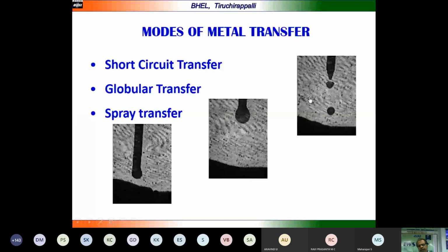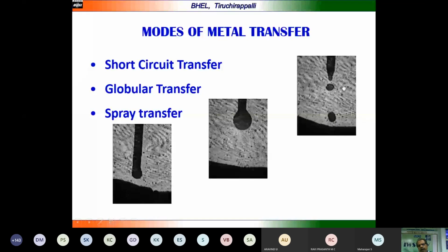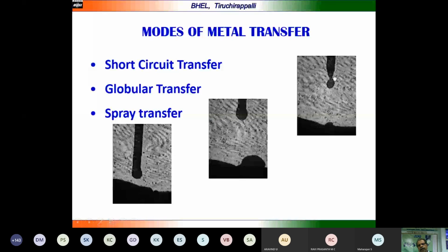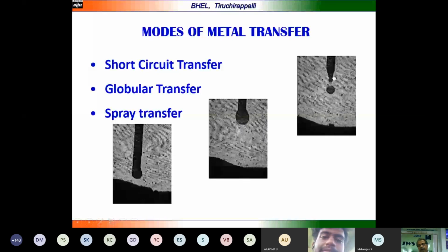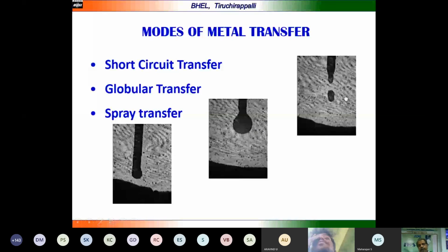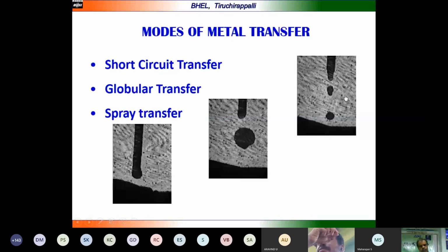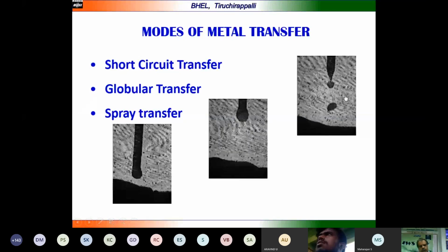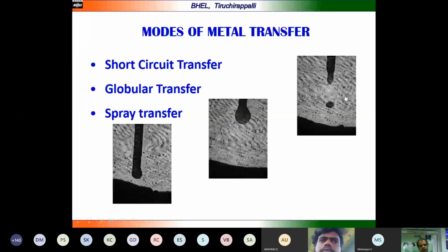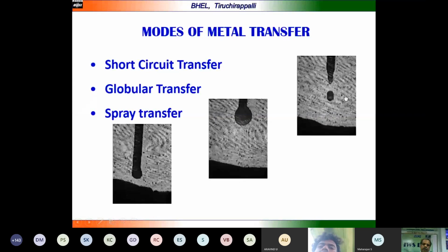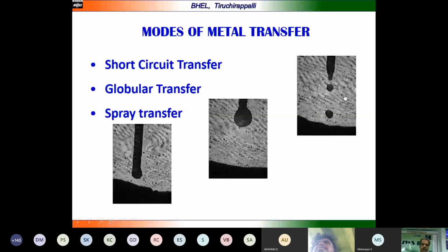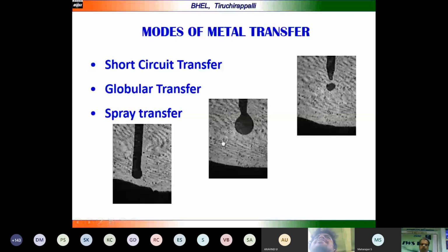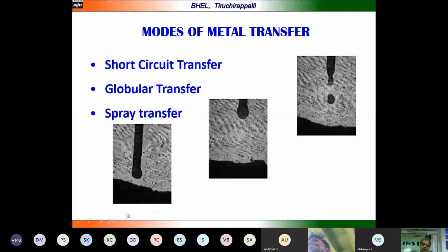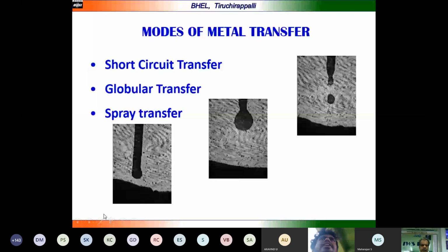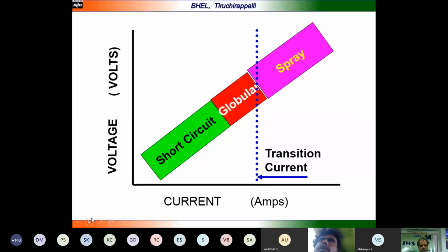You can see a continuous spray of metal droplets into the weld metal. Because of that, the weld quality and the weld metal deposition rate are very high. Very high current can be used in this process. But the short circuit transfer can be used in the overhead position also. This is the voltage and current region for short circuit, globular and spray transfer, shown schematically to you. This is a transition where the globular transfer is getting converted to spray transfer for highly productive applications.